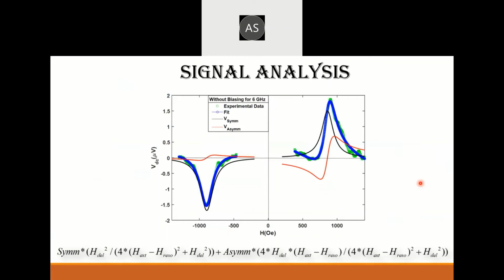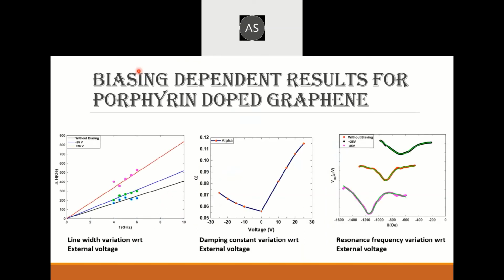Now, the analysis of the spectra is pretty simple. What we did is that we have used a function which is the sum of a symmetric Lorentzian and an asymmetric Lorentzian, and we fit it on top of our experimental result. The values that we have noted from here are the resonance field and the delta H. Now, what we have found is that if we apply a gate voltage and we plot this delta H for different gate voltages, we will see that this actually modulates. So you can find that the slope actually changes with respect to voltage.